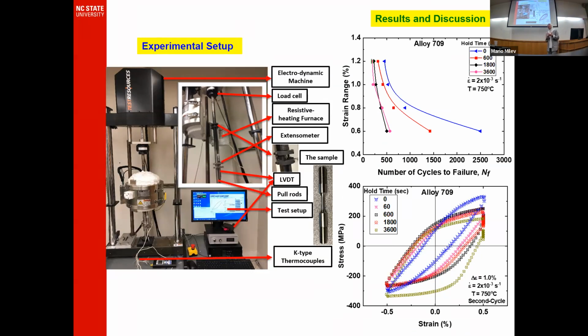We performed it at different temperatures, like 650 degrees Celsius and 750 degrees Celsius, and at different hold times. Hold time refers to creep damage, because as we can see in the stress-strain hysteresis loop, here is the fatigue part, but the creep part is referred to by this area.